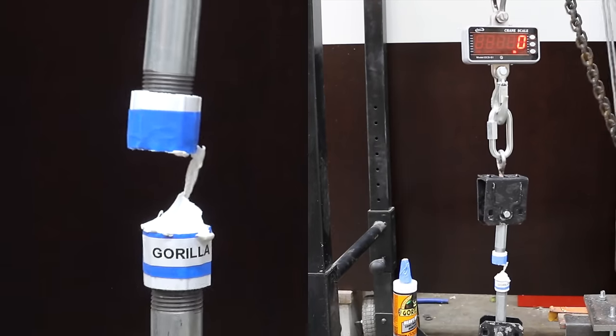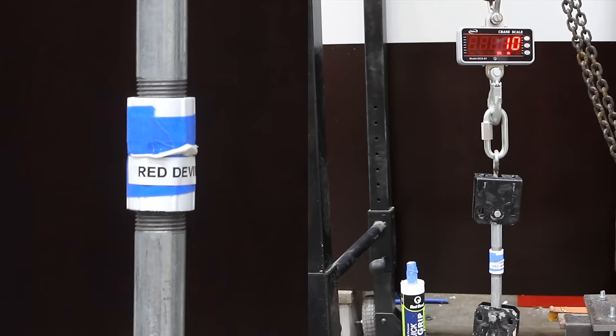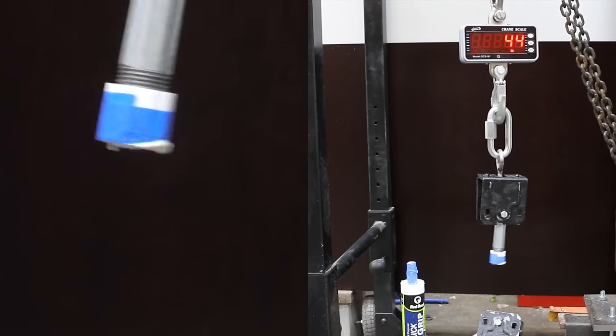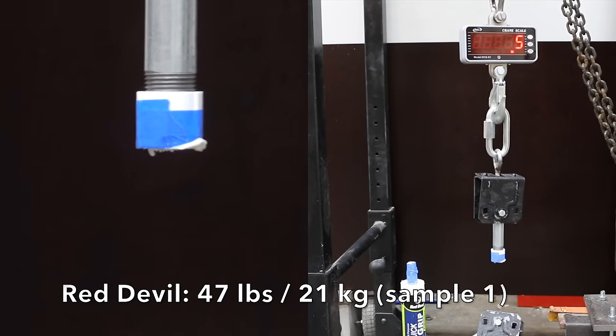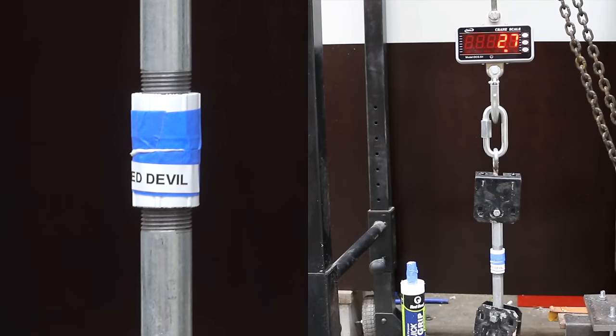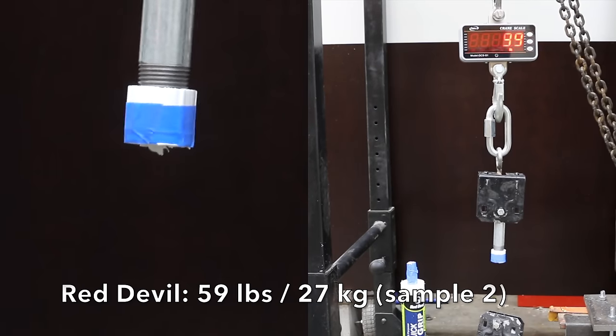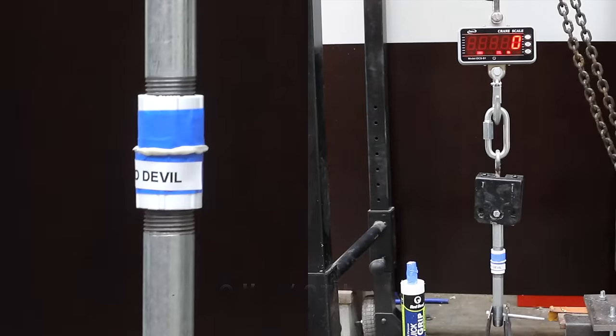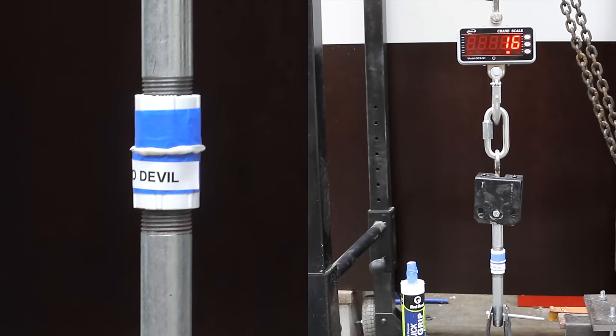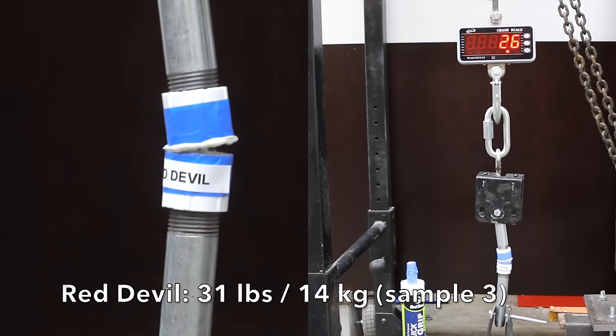Let's see if Red Devil can do any better. Just like F-26, unfortunately Red Devil isn't curing in the center of the PVC, even though it did just fine curing with wood. The second was up a little to 59. The third was down a little. It would have done a lot better if the adhesive had fully cured.